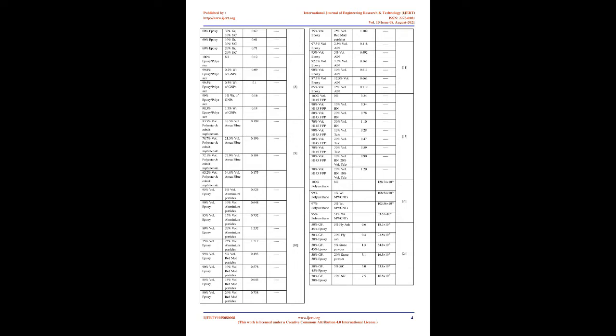High thermal conductivity GNPs added to epoxy resin, E51, causes to develop a lower interfacial thermal resistance in epoxy resin, which influence the transport of phonon, in turn increases the thermal conductivity of GNPs epoxy resin nanocomposites. Also the GNP/E51 composites exhibit high glass transition temperature, due to GNP's surface molecules react with epoxy resin, which increases the strength of interface bonding between GNPs and epoxy resin, E51.